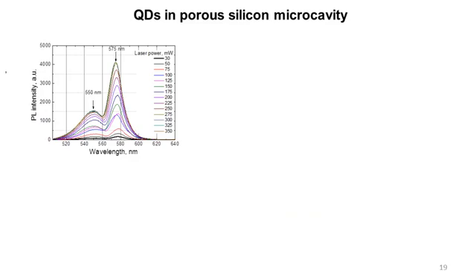One can see that after embedding of quantum dots into the microcavity, their spectra split into two peaks. The first one at 575 nanometers with width of about 50 nanometers corresponds to the wavelength of the microcavity resonant mode and may be related with the effect of weak coupling of quantum dots with the resonant mode. The second peak at 550 has the same width as the initial ensemble of quantum dots in the solution and can be attributed to the uncoupled part of the ensemble.